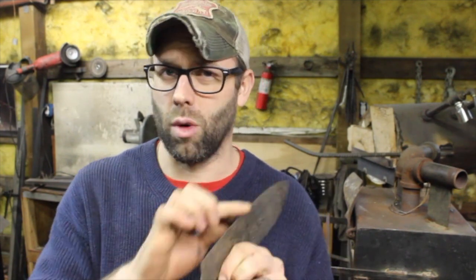Well, there is that, but in this case we're dealing with 1095 high carbon steel and 15N20, neither of which are a deep hardening steel. A deep hardening steel does not require the same speed of quenching that your other steels do. In the case of 1095 and 15N20, the window of time for that steel to cool down to a certain point out of the kiln is very, very short. If you have a thicker piece of steel, the chances of that steel reaching that temperature in the needed amount of time are less. Therefore, I have ground this down to relatively thin for a rough grind in order to ensure that I'm going to get full hardness at least a good portion up the blade.